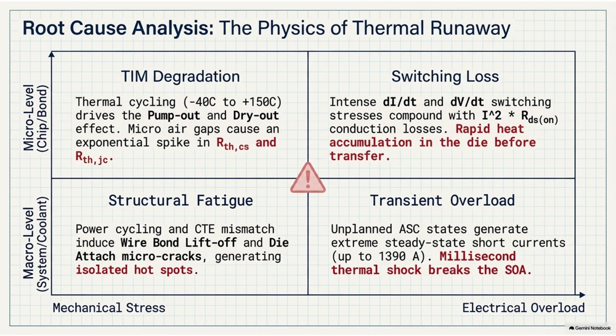Exactly. It's like taking a full tube of toothpaste, leaving the cap off, and repeatedly freezing it solid, boiling it, and stepping on it. That is precisely what happens. The cyclic warping physically forces the thermal interface material out from between the layers. Oh, wow. The paste gets pumped out, or the extreme heat just bakes the oils out of it, leading to what we call dry-out aging. And when that paste migrates out, it leaves behind those microscopic air gaps we just talked about. And here is where the physics turn deadly for the module.